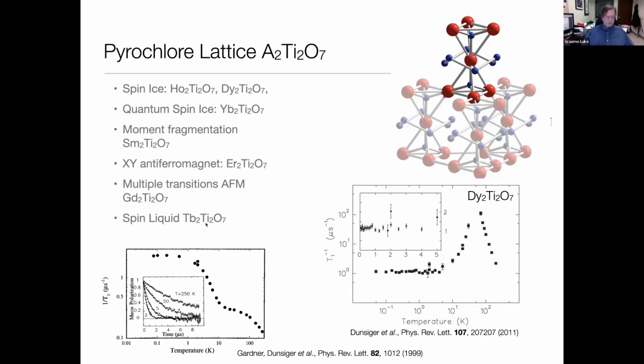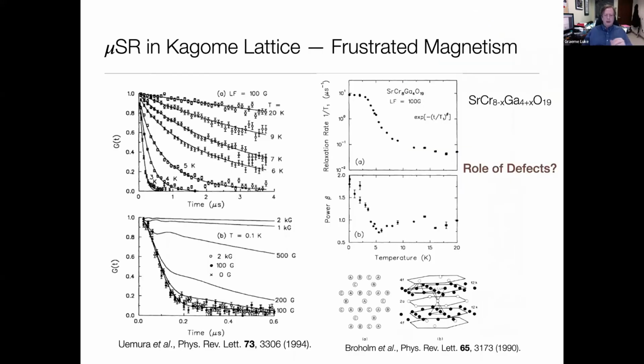There's other materials like terbium titanate, where this is a plot of just a spin lattice relaxation rate. And you see that as you get down to low temperatures, it becomes temperature independent. And these fluctuations apparently persist to the lowest possible temperature. Here we're down to about 50 millikelvin. So this is a potential quantum spin liquid, which has been a real holy grail for condensed matter physicists for quite a while. The Kagome lattice is something that's been studied for a long time.